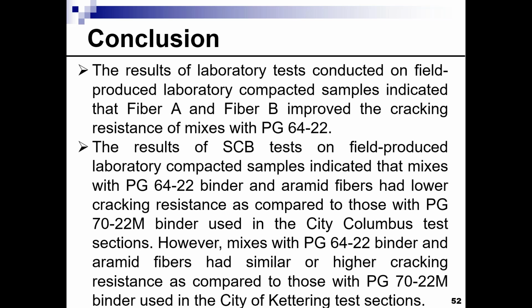Now, if we're comparing the results of the PG 64-22 with the Aramid fibers, as compared to the 70-22, in terms of the SCB, we have seen that in the city of Columbus, the 70-22 polymer modified actually outperformed the fiber in terms of cracking resistance, again based on the SCB test results. But when it came to the city of Kettering, they had either similar or higher.